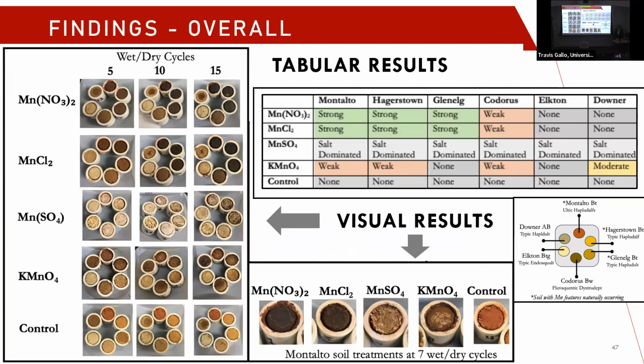Here are the results of this experiment. The visual results here, I've highlighted where the manganese coatings were formed most strongly. They were formed in soils that happen to already have manganese features and in the solutions of manganese nitrate and manganese chloride. You can see below the control did not form any coatings. Potassium permanganate did not form any black coatings. Manganese sulfate resulted in the accumulation of sulfate salts, which were primarily gypsum.